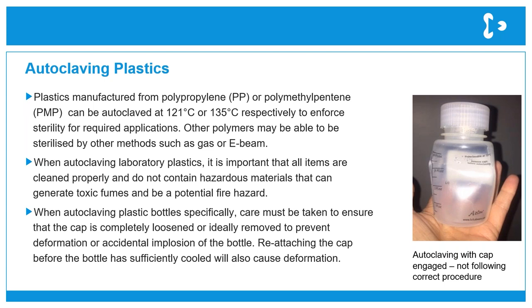And this could be ethylene oxide gas and e-beam sterilization. As I mentioned before, it is very important that prior to autoclaving, products are cleaned because they can contain hazardous materials that can generate toxic fumes or present a fire hazard. And specifically with bottles, care must be taken to ensure that the cap is completely loosened or ideally removed to prevent the implosion that we saw on the previous slide.